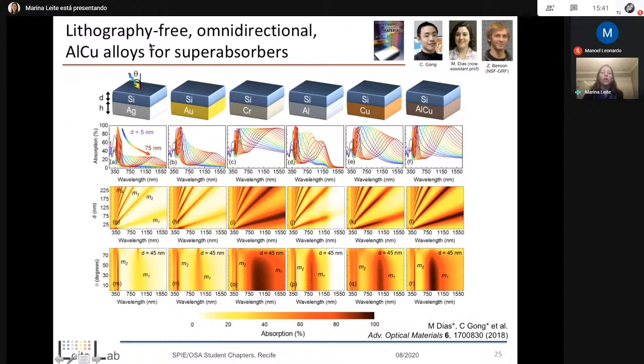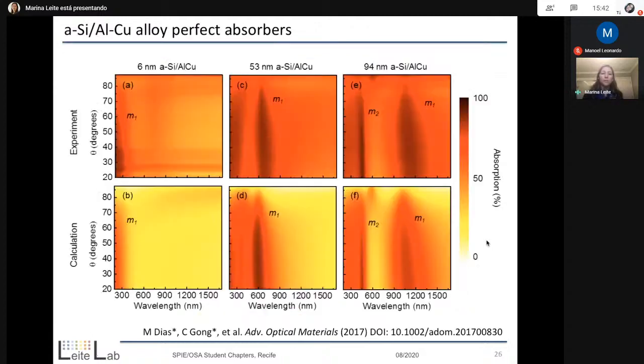And even more so, if we change the angle of light incidence, represented by theta, we can see that it's pretty robust, up to almost 70 degrees. So it's almost omnidirectional, which I think is really neat as well, because a lot of times we suffer a big penalty by doing an angular incidence.